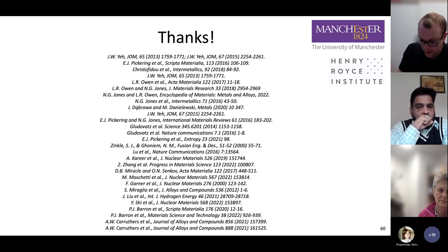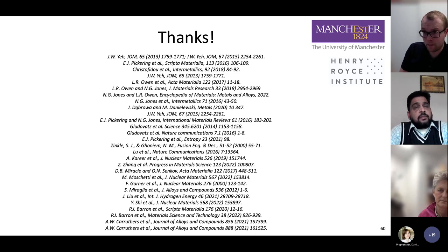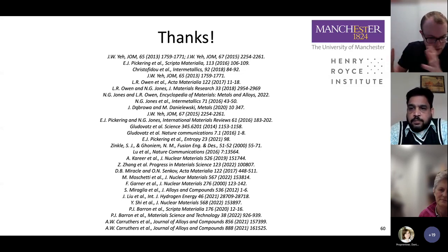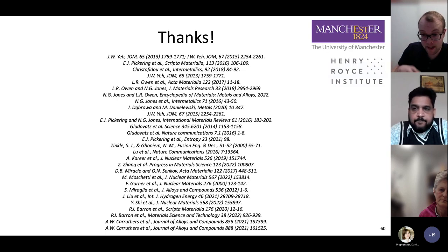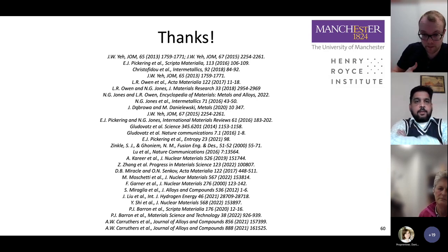Firstly, and this one isn't really about learning, but more about enabling research, a lot of the high entropy alloy work has forced thermodynamic database providers to assess their binary, ternary, and quaternary systems much more rigorously than they have been asked to before. And I think that's only a good thing if we're looking at developing really exotic, high temperature, high strength power plant concentrated steels, for instance. If we're going to introduce all sorts of crazy precipitates and alloy them a lot, or maybe introduce some new TWIP steels, I think it's only a good thing that the thermodynamic databases are being more rigorously tested by the high-entropy alloy community, and that is being fed through into steels. So that's the first thing.